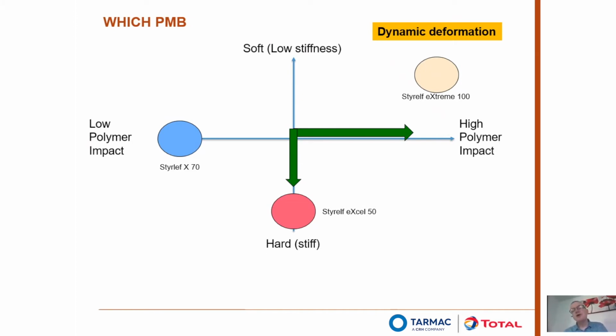But also you can go with higher polymer impact because that means the road becomes more elastic, so it recovers more. And with something like Styrelf eXtreme 100 right at the far end of the polymer impact scale, where we've got a high polymer impact, we're getting really good recovery. So that means that the amount of permanent deformation, even though it's quite a soft material, is restricted. Okay, so what we would say is that you wouldn't choose something where you're going to have concerns about dynamic deformation. I wouldn't be using something like a Styrelf X70 because it's not got the contribution there from the polymer that it needs to resist that dynamic deformation.